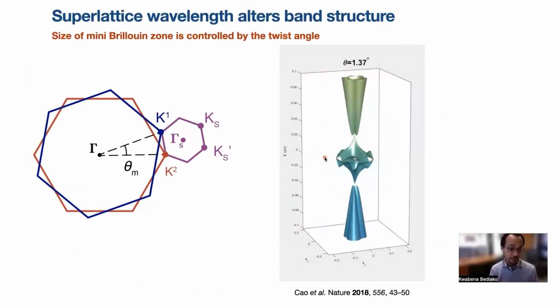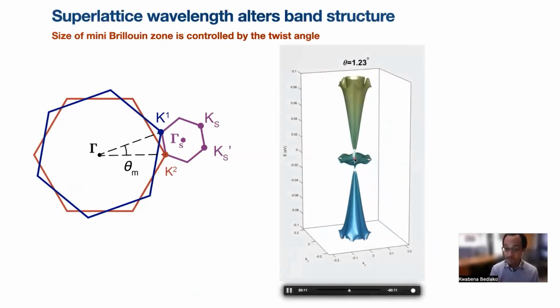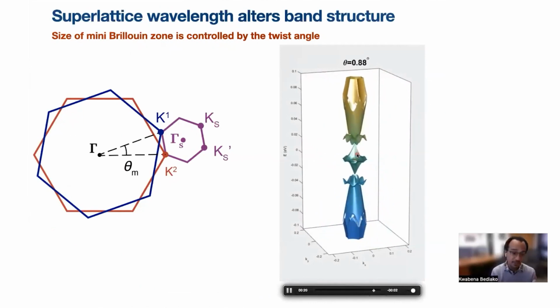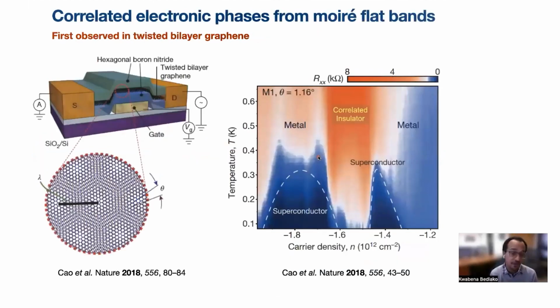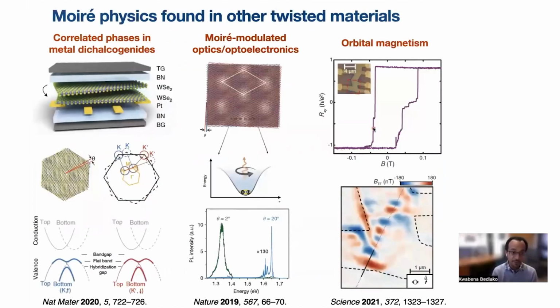And it wasn't until about 2018 or so that the full potential of these flat bands was realized in the discovery of correlated electronic phases in twisted bilayer graphene. And so there's been a surge of interest in these Moiré-based systems, particularly for the exciting and exotic low temperature physics that they display. And this is not just the case for graphene, but across the family of atomically thin layers, these Moiré materials have been shown to exhibit a wide array of twist tunable electronic properties.